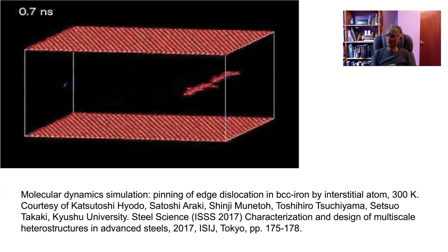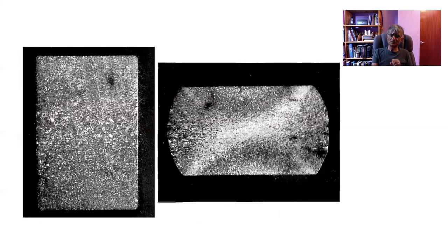So imagine what this cluster of dislocations that I illustrated, caused by the plastic relaxation of austenite, would do. It would completely kill the glissile interface, which consists of an array of dislocations. It simply would not be able to move. So the bainite plate would grow to a certain size and then kill itself by the plastic relaxation that has happened. The interface can no longer move. So this is an effect called mechanical stabilization. If the austenite contains quite a lot of defects, then it will tend to retard displacive transformations.